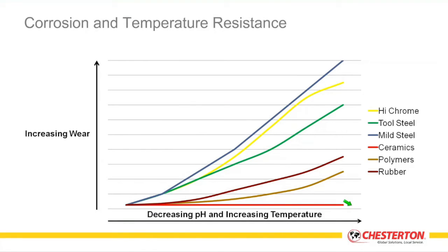And finally, when we look at corrosion and chemical resistance, because sometimes these abrasive conditions are present in a slurry or a corrosive solution. These corrodants can be chlorides, sulfates, or various acid-based compounds that might be used in the leaching process, and these will also have a high impact on the degree of wear. Because as metals, or any material, react with the chemical environment and oxidize, it becomes a passive layer. That passive layer is weakly bound, and then flow, particularly a flow with embedded suspended particles, can cause accelerated wear.